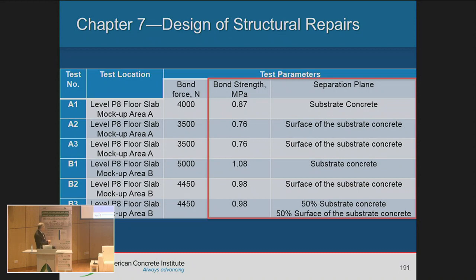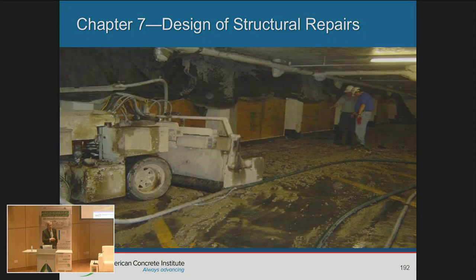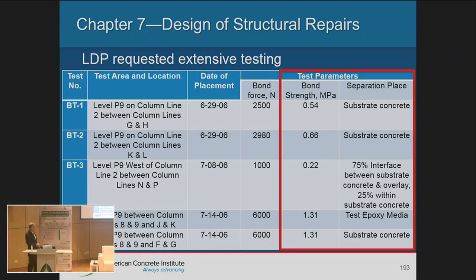Because if you look at those low ones, the failure was at the surface of the substrate concrete. So it wasn't really at the interface. So here they started with the construction work. Here's the equipment that's doing the hydro demolition within the structure. After they had done some work, the engineer said, let's stop and check what we have done so far as quality control. Do we have good bondage? Do we have proper bondage? When they did some testing, they found tests that were very low, 0.22, and it is at the interface, 0.54. So very low test results.